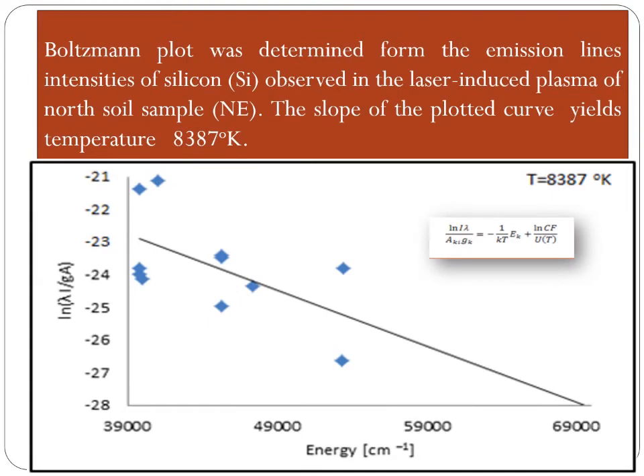This is the Boltzmann plot for the collected soil samples, which gives us an estimation of the electron temperature of about 8387 Kelvin, which can be calculated from the slope of this curve.